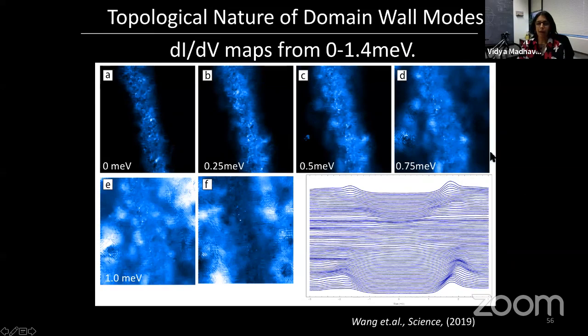So that's what happens to this boundary state. These are now not topographies, but dI/dV maps. So we are measuring the density of states at different energies and plotting that as a function of position. Here at 0, this is actual data. When it's dark like this, it's truly 0 density of states. At 0 millivolts, which is the Fermi energy, you see no density of states anywhere except at the domain wall. So this is the domain wall mode.